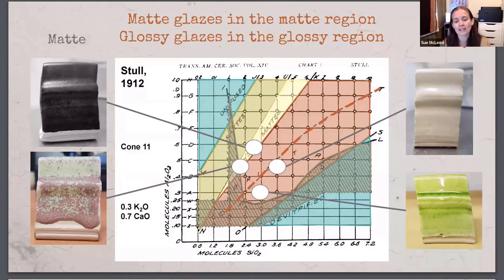It's cool when you start learning this, you can enter all your glaze recipes into Glaze, look at the UMF, and Glaze will plot your glaze recipe on the Stull chart so you can see where it falls. If it doesn't fall where you expect, then you can look and see if you can understand why. Why is my glaze in the glossy region? Why is it matte? It could be matte because it's underfired. It could be matte because it contains titanium. Titanium, also rutile, crystallizes during the cooling cycle, which can turn a glaze in the glossy region matte. So there are nuances and reasons why your glaze might not match these patterns, but those are all things we can learn when we understand the chemistry.